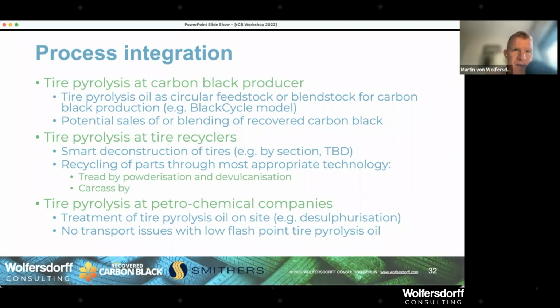Then also a case I have looked at, tire pyrolysis at petrochemical companies, and that could be, it wasn't my case, but it could be BASF and Pyrum. So you could have the treatment of the tire pyrolysis oil on site. One trouble, let's say two troubles for the tire pyrolysis oil. One is extremely low flash point, which makes the transport quite difficult. But if we have the tire pyrolysis site within the conglomerate of the petrochemical industry, within the refinery, then the transport is no problem. Flash point is no problem. Sulfur might be a problem, depending on the mass balance and the technology of the pyrolysis. Of course, the higher the temperature, the more the sulfur will go in the gas, not in the oil.